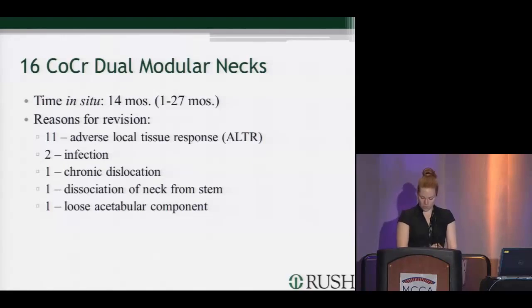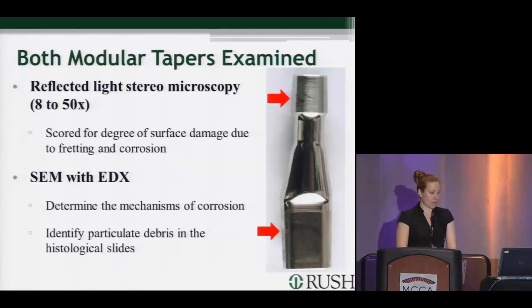These 16 cobalt chrome dual modular necks were retrieved after a mean of 14 months. The primary reason for revision was adverse local tissue response. Both the modular tapers were examined. Reflected light stereomicroscopy was used to score the degree of surface damage due to fretting and corrosion. Scanning electron microscopy and energy dispersive X-ray analysis were used to determine the mechanisms of corrosion, as well as to identify particulate debris in the histological slides.